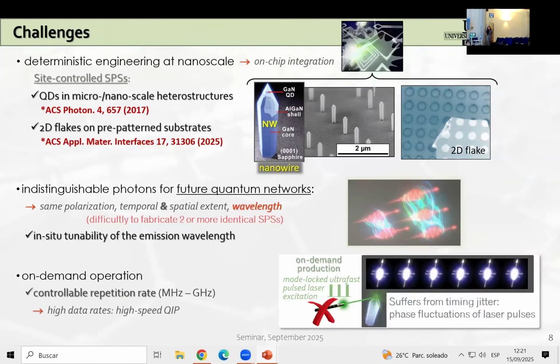Another requirement is the on-demand production of single photons with controllable repetition rate at megahertz or even higher frequency range, which is still an issue for high-speed quantum information processing. So what is typically used to produce on-demand single photons are ultra-fast pulsed laser excitations. However, this method of excitation suffers from jitter in the photon emission time, and this is mainly due to the phase fluctuations within the laser pulses, even when they are operated in a mode-lock regime. So it would be convenient to find another method that could suppress such jitter.